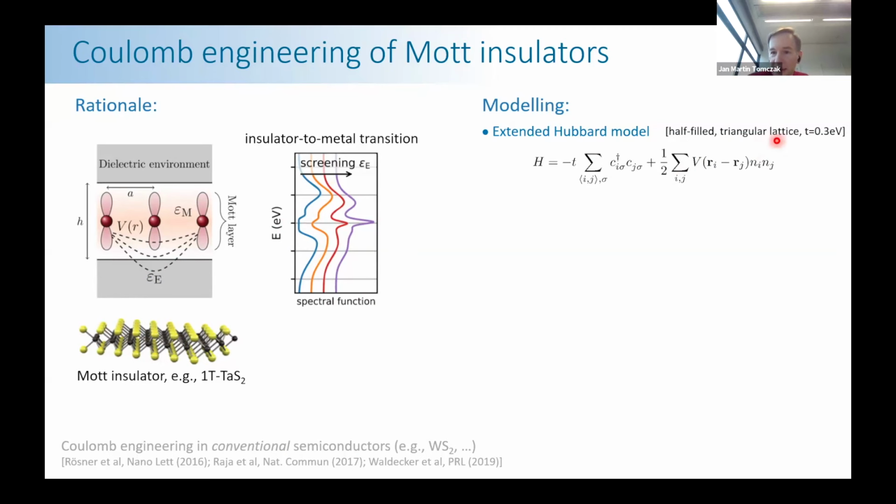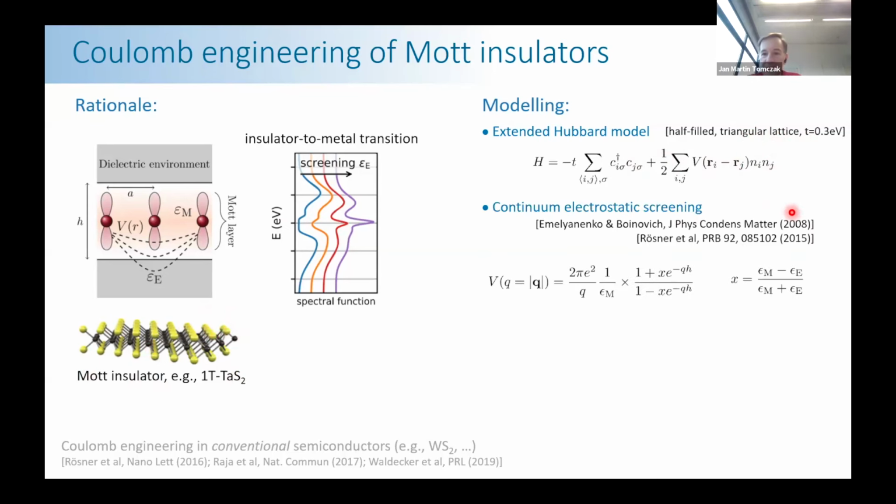And so the way Eric models this is we use an extended Hubbard model here, on the triangular lattice, because our motivation is transition metal dichalcogenide structures, with the long-range Coulomb interaction. And indeed, the reason we need this long-range Coulomb interaction is that screening is not just dynamic, but also has to do with the range. Screening, in particular in 2D systems, is imperfect. So there is a lot of remnant of the unscreened 1/r Coulomb interaction, and so this is important here.